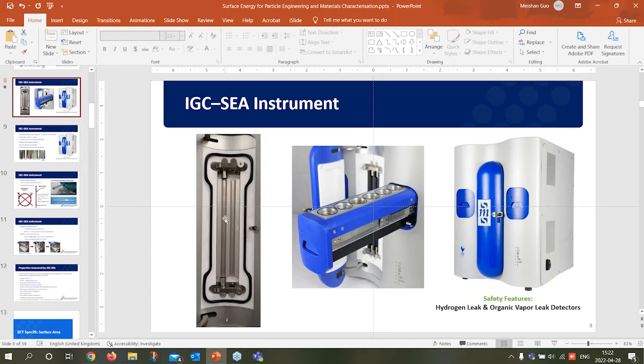Someone asks here, do you have to dilute solvents for the IGC instrument, or does the instrument dilute the organic solvents? If it does, what compound is used for this dilution? So basically, we don't need to dilute it ourselves. All the injection is automatic injection from the gas phase of the reservoir. So we have each solvent here, and the mass flow controller will control the carrier gas, which is nitrogen or helium, for different ratios of the carrier gas and the vapor. And then we will have a calibration of the FID to detect the concentration. So we don't need to do the dilution, but the dilution is performed by the helium or nitrogen carrier gas.